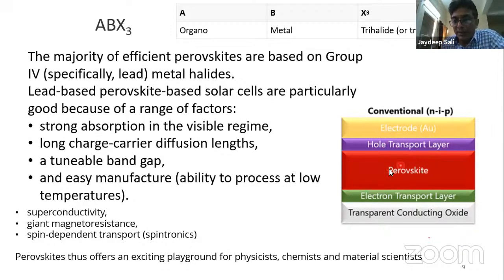It contains different layers that are used in such a solar cell structure. A perovskite material is a photoactive material which absorbs the light and generates free electron hole pairs. So naturally, it must have a strong absorption in the visible regime. Lead-based perovskite solar cells show a strong absorption in the visible range. Secondly, once the free charges are created in the perovskite, they must diffuse towards the respective electrodes, that is, towards the hole transport layer and the electron transport layer.